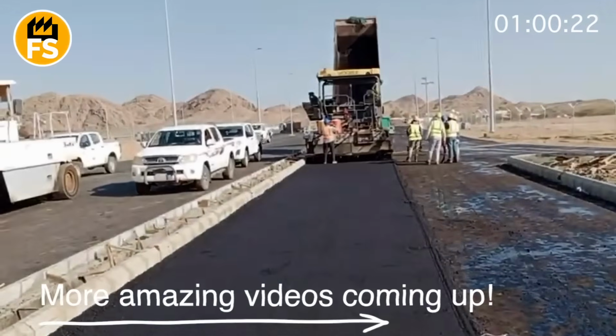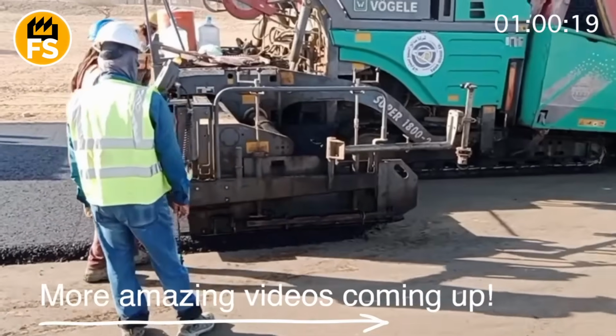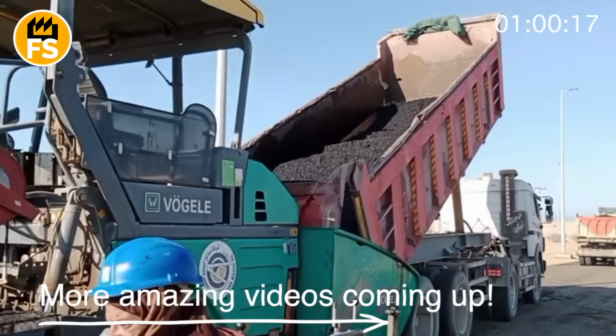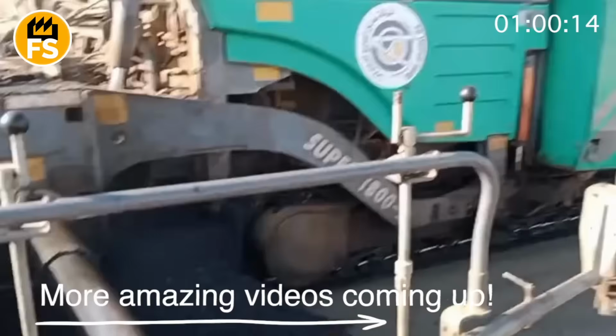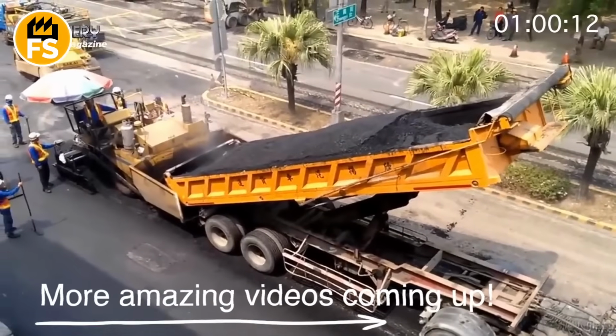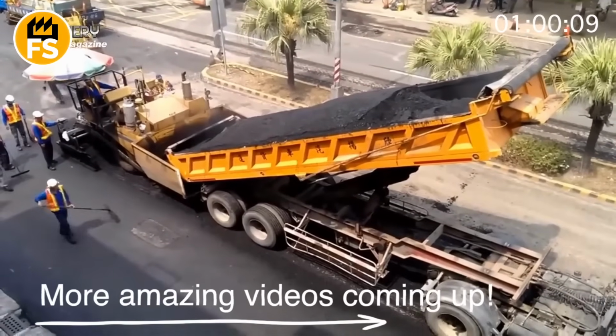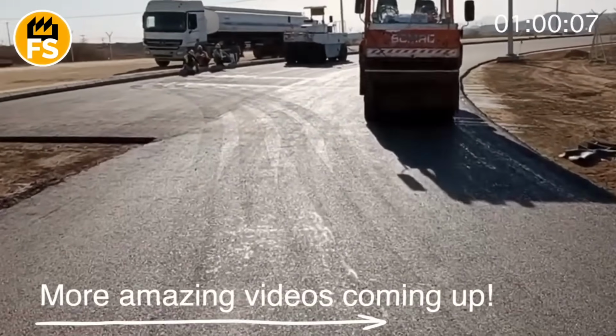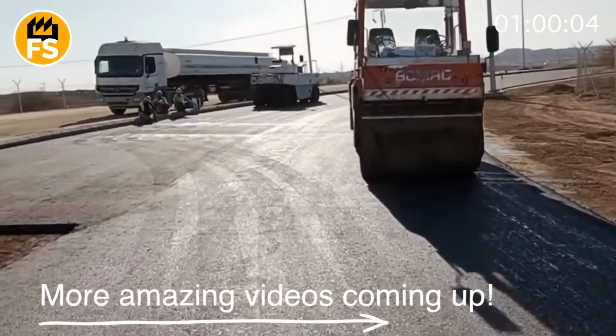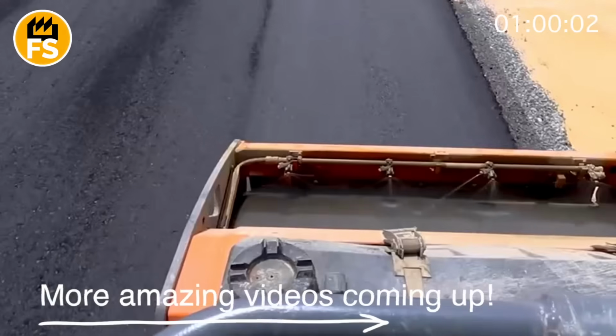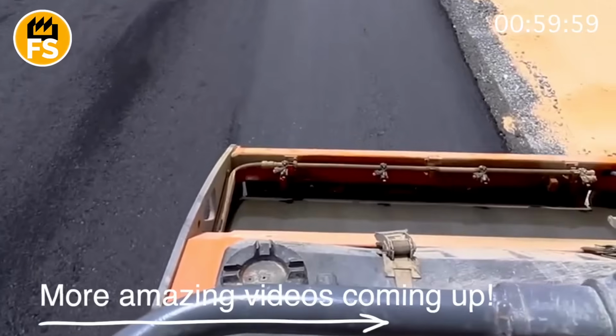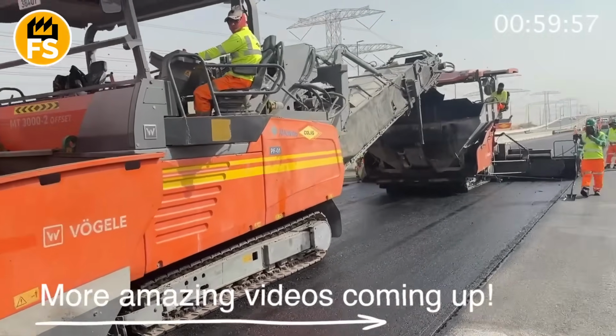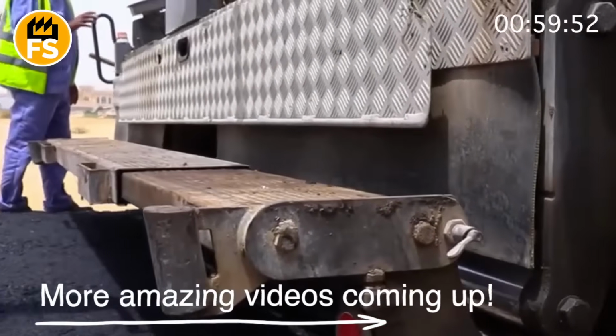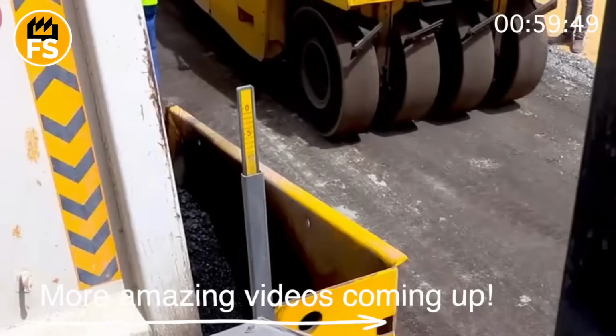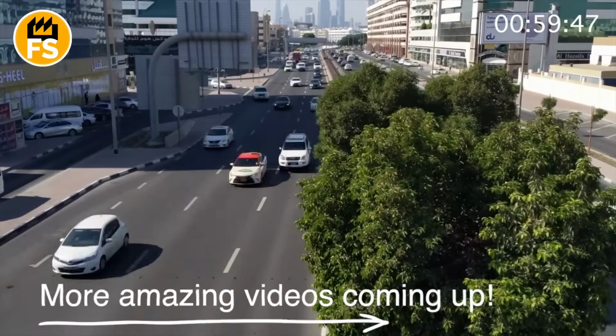Over 1 million tons of asphalt are produced annually in Dubai, and this figure is growing along with the expansion of infrastructure. The DxB Asphalt Factory alone has a capacity of 240 tons per hour, which allows for supplying large projects without interruptions. For comparison, an average plant in Europe produces about 150 tons per hour. Interestingly, asphalt is the most recycled material in the US, and over 99% of old pavement is returned to production. In Dubai, recycling is also being actively implemented, especially during the reconstruction of old roads in industrial areas.